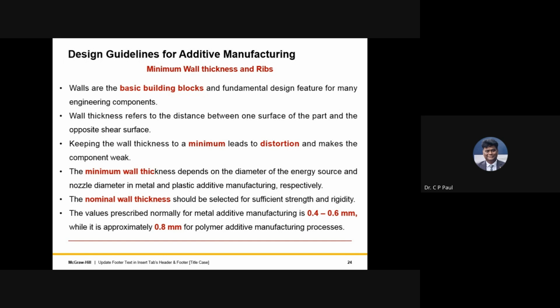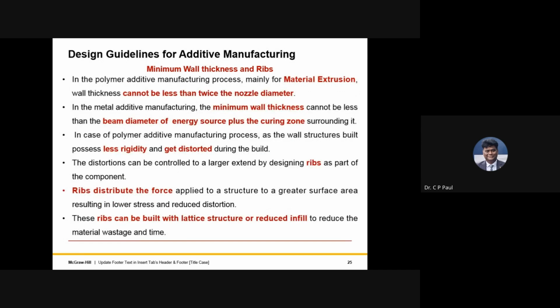In general, for metal additive manufacturing, a wall thickness of 0.4 to 0.6 millimeter is fine, and in polymers, a 0.8 millimeter thick wall can be built easily. This is the number which is available so far. In polymer manufacturing, we are mainly using material extrusion processes like FDM. You cannot go less than twice the diameter of the nozzle. For example, if you are using a nozzle of 0.4 millimeter, the minimum wall thickness you can go for is 0.8. That is the minimal criterion people go ahead with.